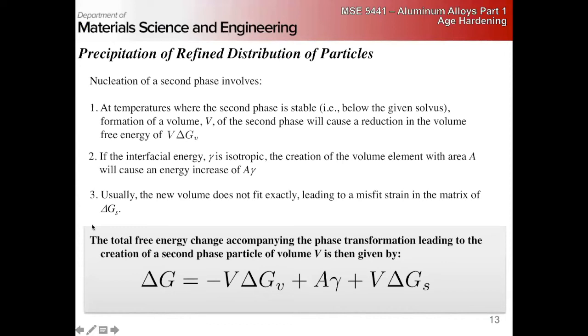We also have a lattice strain term because the volumes of these are not exactly the same. We have different lattice parameters. So that's going to give us a misfit strain that can either be, right, if our particle is denser than our matrix, we're going to have a tensile strain in the matrix, right? If it's larger, we're going to have a compressive elastic strain.